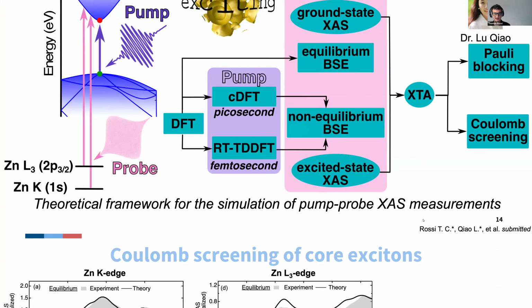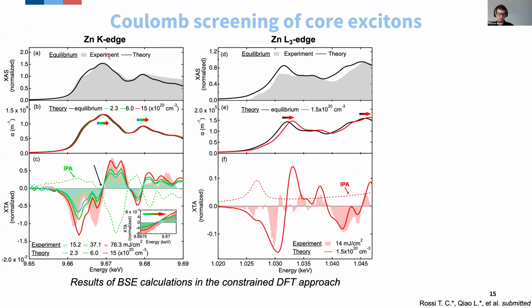And the results of the calculations are these ones. So I want to send a universal message here. I put the zinc K edge and the zinc L3 edge results side by side. In the top panel, you can see how well the theory does to reproduce equilibrium spectra, theory with the continuous black curve, experiment with the gray dashed curves. In the panel below, this is the result of the constrained DFT. So we are manually exciting a given density of excited carriers, and we observe what effect it has on the X-ray absorption spectrum. And what is very exciting here is that we are able to reproduce the blue shift that we observed in the experimental data, which looks pretty much like a rigid shift to the right.